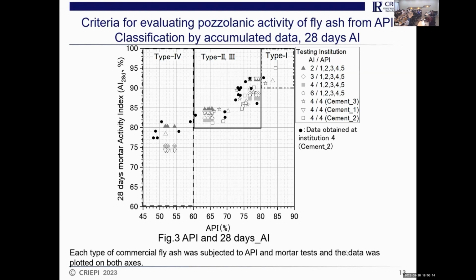And by the way, for the vertical axis, there's a linear relation like those plots. And for type 1, the lower limit was determined as 80% in API. And for type 2 and type 3, we determined the lower limit as 60%. And for type 4, we determined the lower limit as 45% as this.